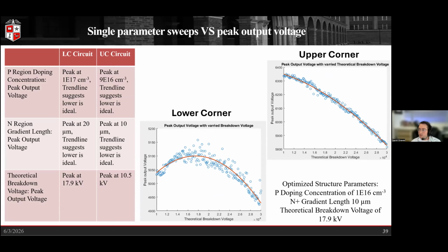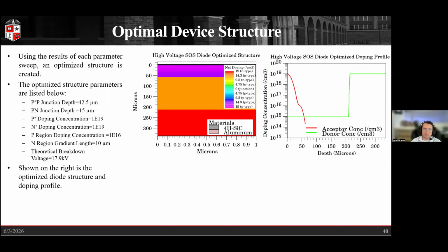And so one of the reasons why we see that is because there's a crossover point. Because of how much charge we're storing in the device, that changes the operation of the circuit. As I mentioned, you really need to optimize the circuit around the device, or if you have a fixed circuit, then you want to go and optimize the device for that circuit. But based on an overall gain, we went with a theoretical breakdown voltage of 17.9 kV for the single device.